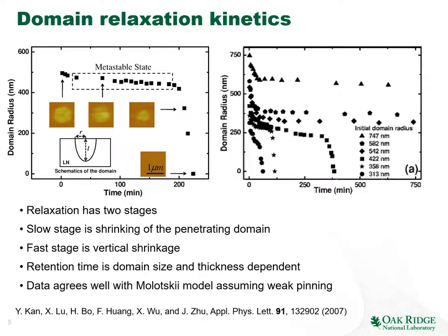This is another example of domain wall relaxation kinetic studies by a group of Zhu and Kan. So they created multiple domains, also in lithium niobate, and they systematically explored the domain size over time. And you can see that the domain relaxation kinetics have a well-defined characteristic shape. So your domain radius stays almost constant for quite some time, and then all of a sudden the domain starts to very rapidly disappear. If you explore the kinetics as a function of the initial domain radius, you will see that a larger domain stays longer, smaller domains disappear much faster,